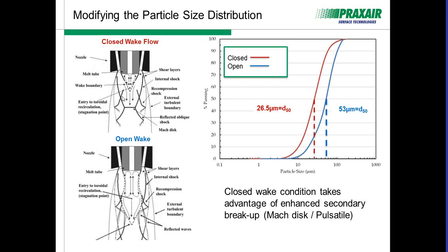This shock structure here represents the shock bottle, and as that high pressure zone enters this shock bottle, it'll force the liquid upwards where it strikes the landing of the nozzle, wets across the nozzle and momentarily interrupts the flow of liquid. When that liquid flow is interrupted, this Mach disk has the ability to recreate this aspiration or suction on the tip of the nozzle, and the liquid starts to flow again. This all happens very rapidly, typically on the order of 35 hertz.